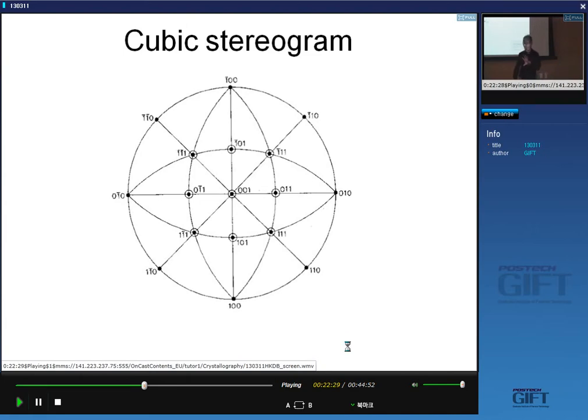So the stereographic projection will reflect the symmetry of the poles that you have. What is the symmetry of the 111 pole in terms of the rotation? So 111 is a cube diagonal. Threefold, and you can see there are three of these great circles passing through the 111 pole. Okay, so everything on here is consistent, and the distances here are angular relationships. So the angle between this and this is 90 degrees, between this and this is 90 degrees, between this and this will be 45 degrees. It's the 011 type plane. And between this and this will be about 54 degrees. You can calculate those angles using vector dot products, for example.